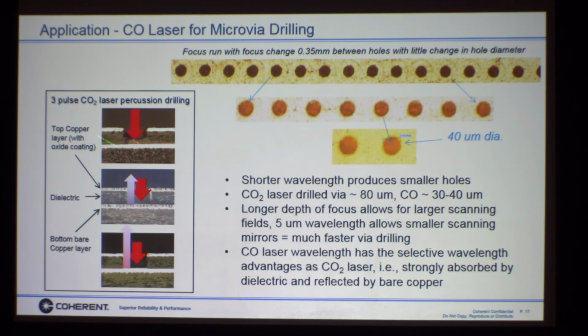And I'll just take a minute to talk about the CO2 drilling process. It's a percussion drilling process in vias. And so typically a via is a hole that connects 2 layers in a multi-layer PCB board, okay? There's typically a copper layer, a dielectric layer, and you can see these here. There's a copper layer, dielectric layer, and another copper layer below. And for CO2 and CO, by the way, we coat the top with the copper oxide layer. First pulse goes through the copper oxide layer and then to some extent down into the dielectric. Second pulse, and it only takes 3 pulses for each hole, goes further down through the dielectric and may hit the next copper layer.